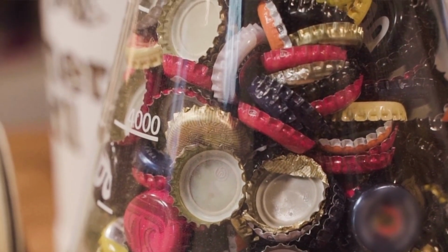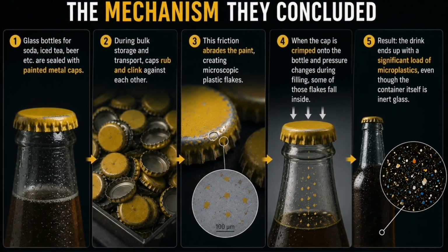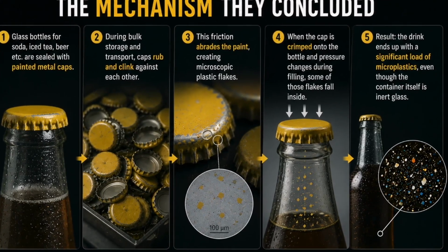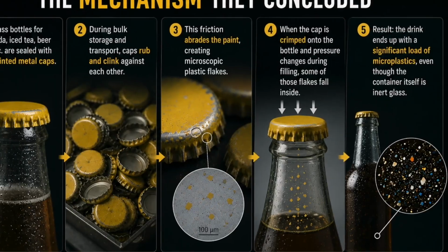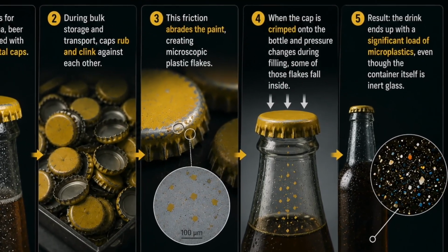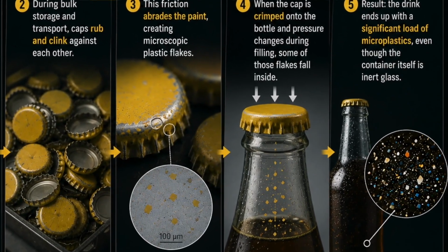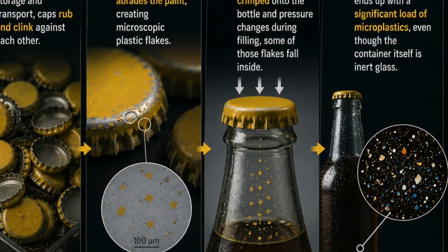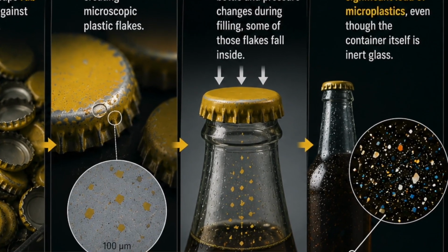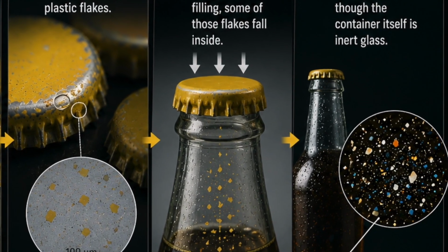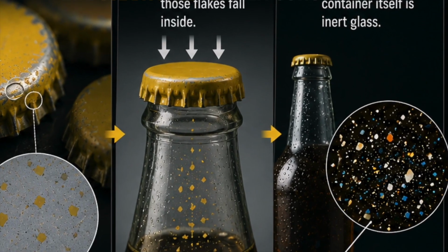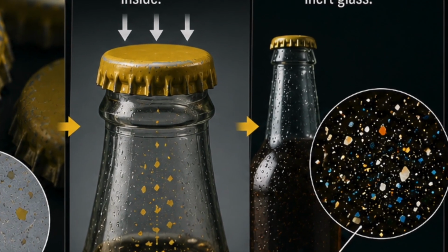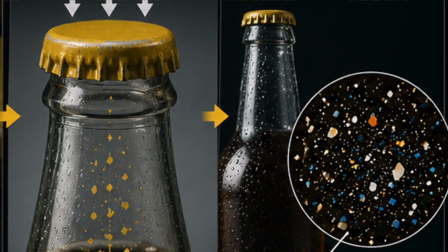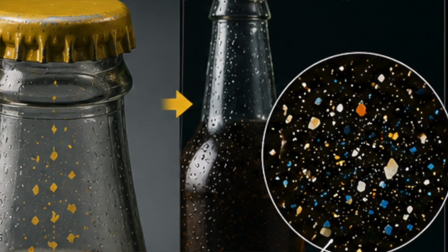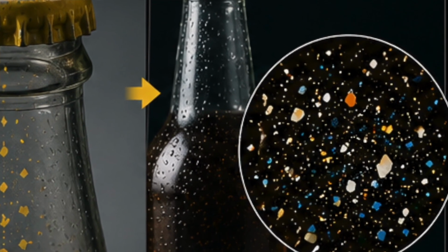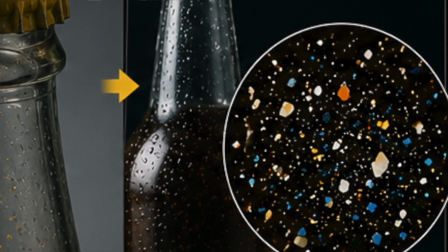Here is the mechanism they concluded. Glass bottles for soda, iced tea, beer, and many other drinks are sealed with painted metal caps. During bulk storage and transport, caps rub and clink against each other. This friction abrades the paint, creating the microplastic flakes. When the cap is crimped onto the bottle, pressure changes during filling. Some of those flakes fall inside. Result, the drink ends up with a significant load of microplastic, even though the container itself is inert glass.